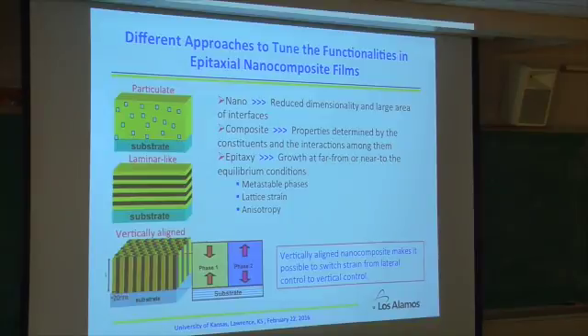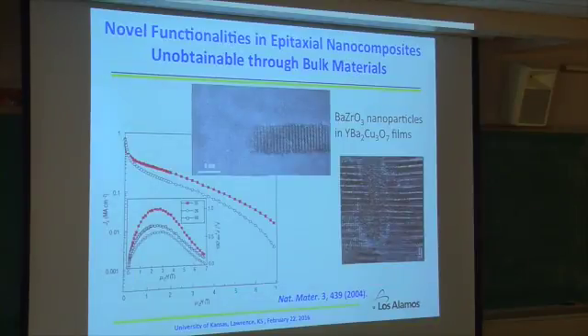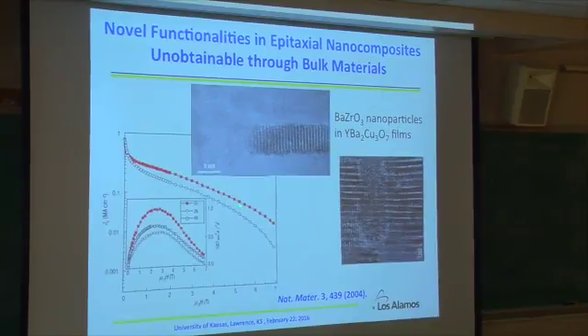Let me give you the first one. It's really nanoparticles, from more than 10 years ago. We developed this: we dope YBCO with barium zirconate. You see here a TEM, where you look at the barium zirconate nanoparticles in the YBCO matrix. The interesting thing is, when you introduce nanoparticles, this one is an insulating phase, but the superconductor is YBCO. Sometimes you might say that's a defect in your material, and typically we say a defect is bad, right? But actually when you do this, you can enhance the flux pinning properties of the superconductor, as people call it.